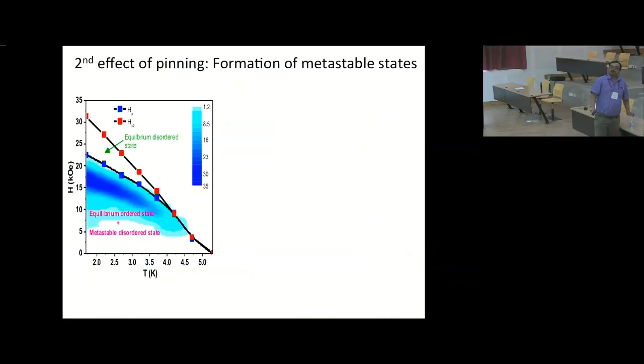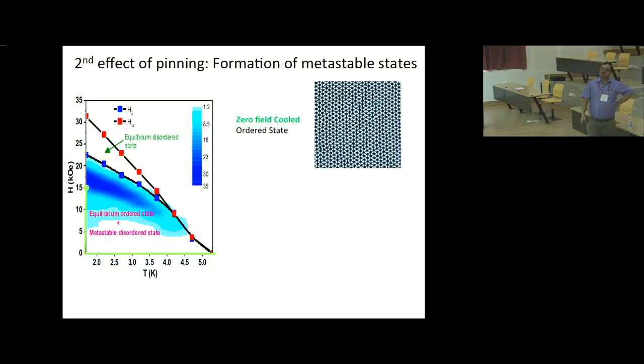All right. So now, before I show you the order-disorder transition, let me tell you there is a second effect of pinning other than giving you critical current, and that's the formation of metastable states. So let's say this is the kind of phase diagram that I have shown you before. And now I create the vortex lattice in two ways. First, I cool it in zero field and I apply 15 kilo-oersted here. I get a vortex lattice which is very well ordered like this.